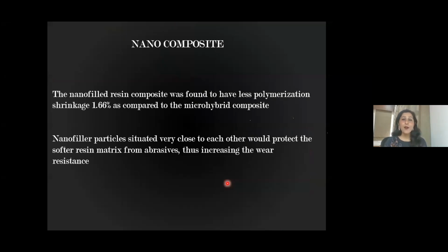Now, nano composites. Where do you use them? The nano-filled resin composite was found to have less polymerization shrinkage. And should I tell you, the polymerization shrinkage of composites is reported with all composites to be between 1 to 6%. And this is the most frustrating thing of composite, this feature of composite, which leads to so many problems. I will talk about them later. So the best thing, now you remember that nano composite was launched because of its low polymerization shrinkage, that is only 1.66% as compared to the microhybrids.